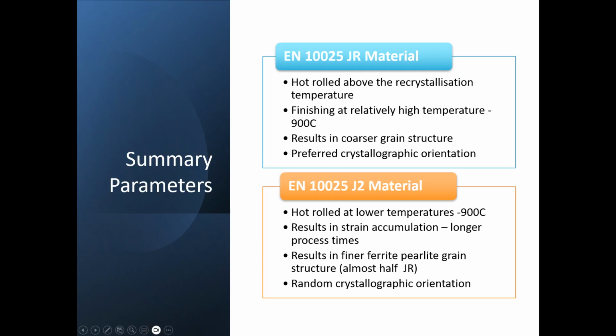But to summarize, JR material is hot rolled above the recrystallization temperature. Recrystallization is the temperature at which, when you deform the grains, they reform again, and therefore would give a bit more resistance to the hot rolling process. They finish it at a relatively higher temperature so that they can put more strain in per pass and roll the coil a lot faster, which results in a coarser grain structure and a preferred crystallographic orientation.